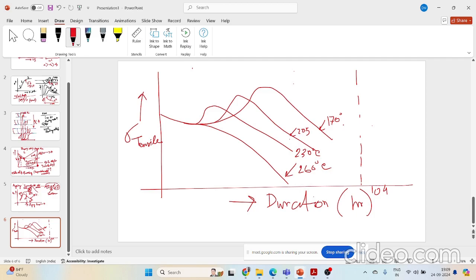So what you will be seeing, the alloy had been naturally aged at room temperature before heat treatment, and the initial strength decreases due to the dissolution of GP zones that formed in natural aging, and the higher the temperature, the faster overaging will occur and the strength decreases, right?